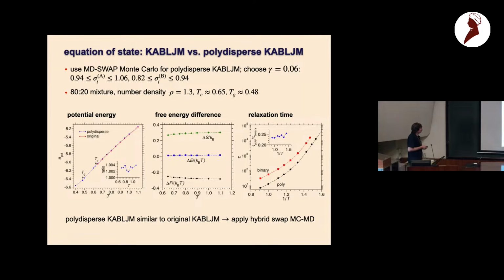We have also applied a thermodynamic integration scheme and computed the free energy difference between the polydisperse mixture and the original binary mixture. So here is what comes out - this is the free energy difference. Of course the energy difference is very small, and what is mainly contributing here, the main difference, is in the entropy. So this is the entropy difference between the polydisperse and the binary system, and this is, at least in this temperature range, pretty constant.